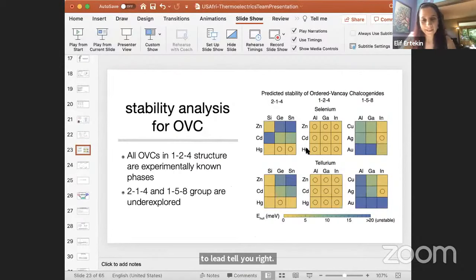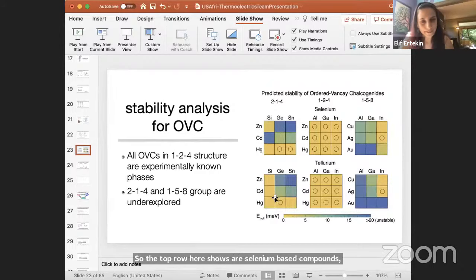Okay, and then at the next level of the screen, we assess the thermodynamic stability of the compound, meaning that we try to determine whether the compound is thermodynamically stable or likely to decompose into competing secondary phases. So the top row here shows our selenium-based compounds. The bottom row shows our tellurium-based compounds. This first column are the 214 stoichiometries. The middle column are the 124 stoichiometries. And the one on the right are the 158 stoichiometries here.